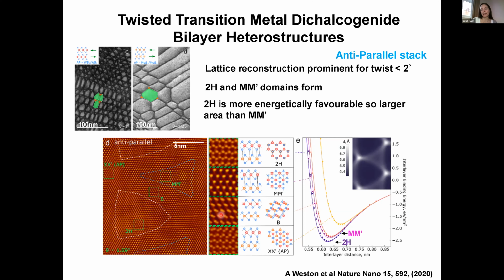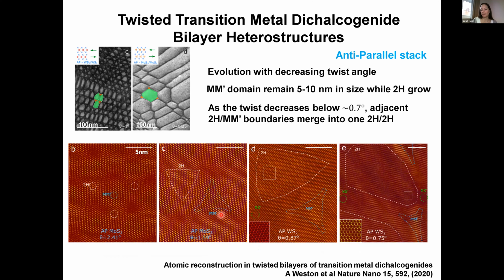So we've looked at different twisted transition metal dichalcogenide bilayers for different angles. The different angles you can see here range from about 2.5 degrees misorientation, anti-parallel stacking. And here you really don't see very much reconstruction at all. But when we start to get down to much smaller angles, you can see that at an angle of just 0.75 degrees, we have a very large 2H domain of perfect commensurate stacking separated by these dislocations with these triangular domain regions.